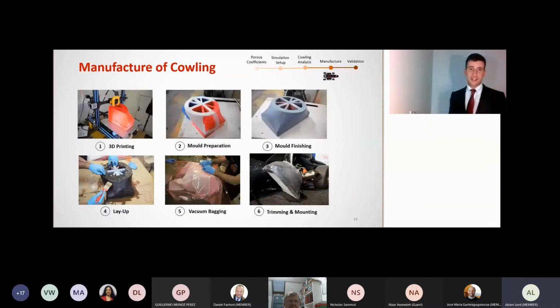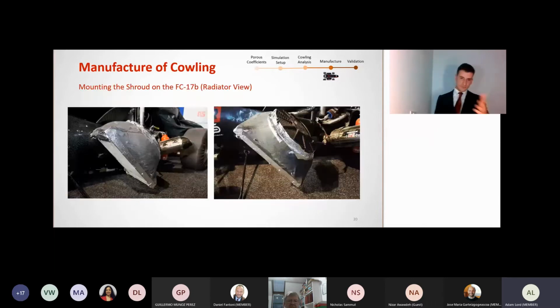It was then decided that the material used for manufacture would be carbon fiber because of its lightweight nature and its high temperature resistance. In addition to this, the team has been fairly experienced in carbon fiber manufacture and has had the resources available to carry out a task such as this. The mold itself was 3D printed due to the complex convex geometry, and this was followed by a carbon fiber wet layup under vacuum. Not only is the wet layup technique the simplest and cheapest method of composite manufacture, but it allowed for the part to be cured at room temperature and hence posed no risk of melting the mold, which was 3D printed. And this is the final